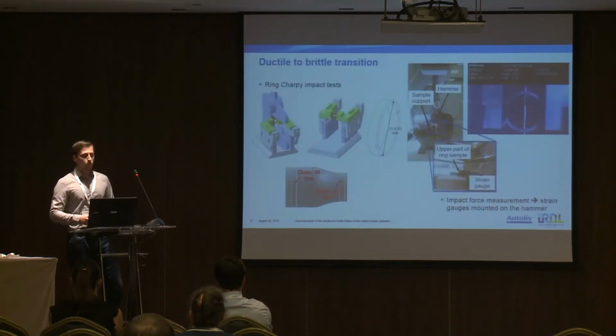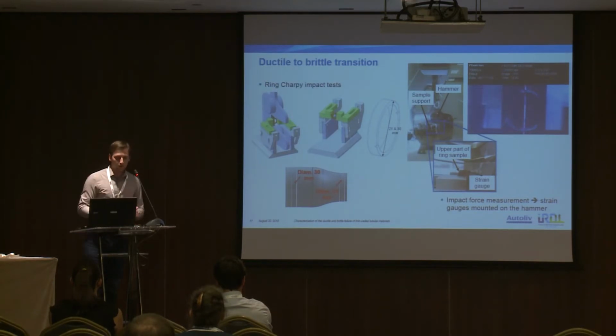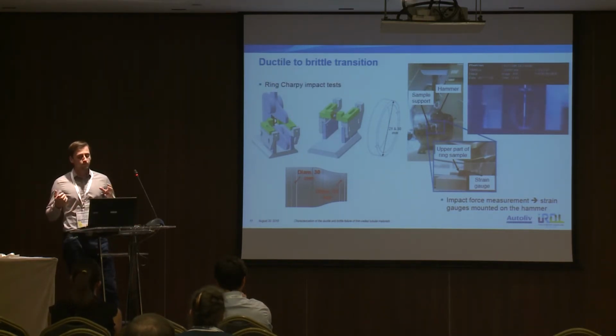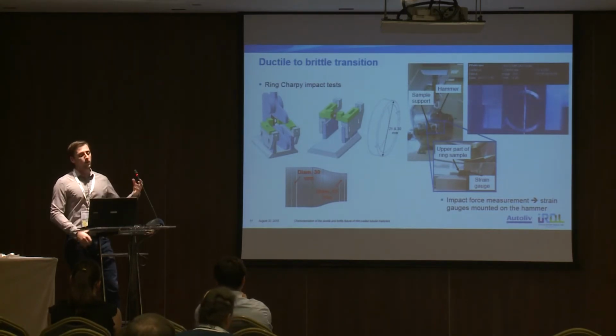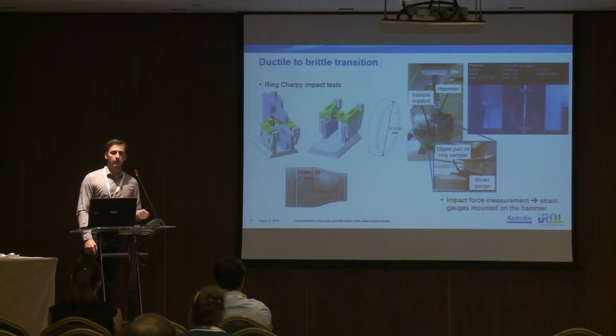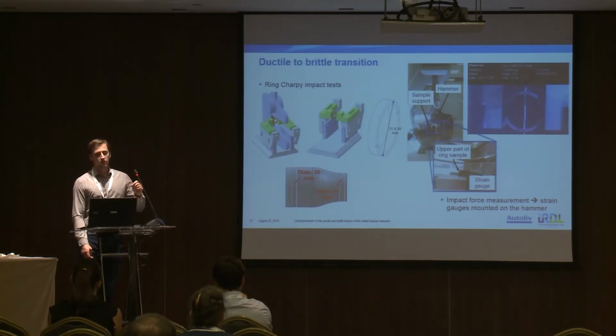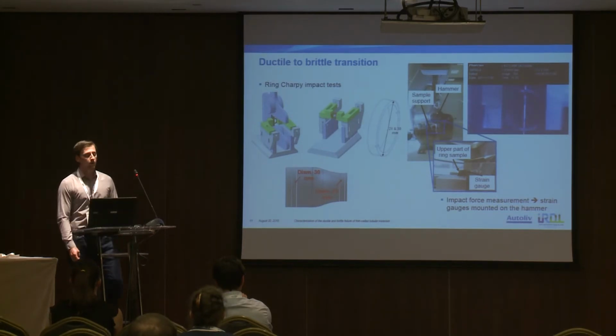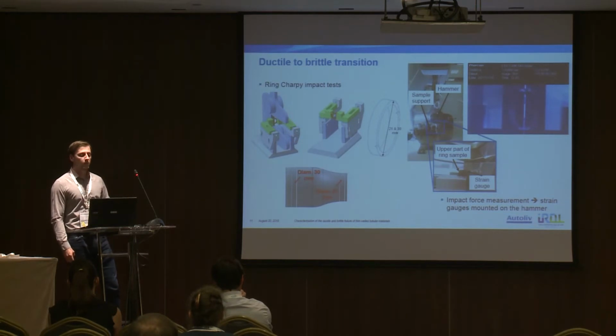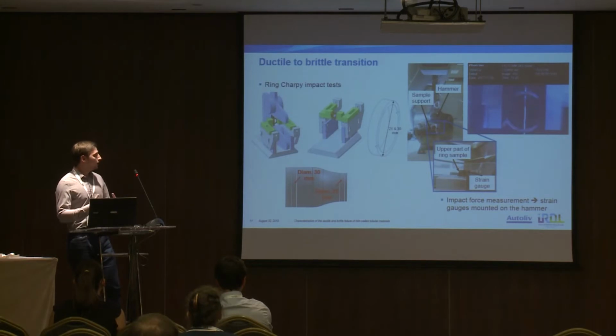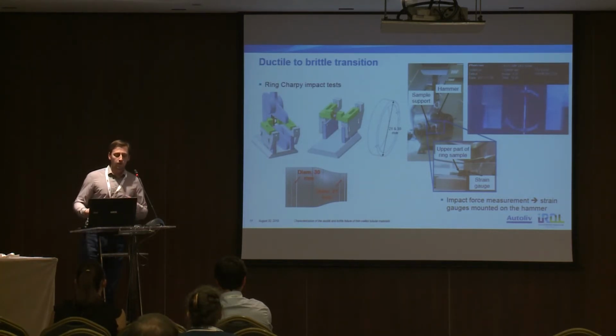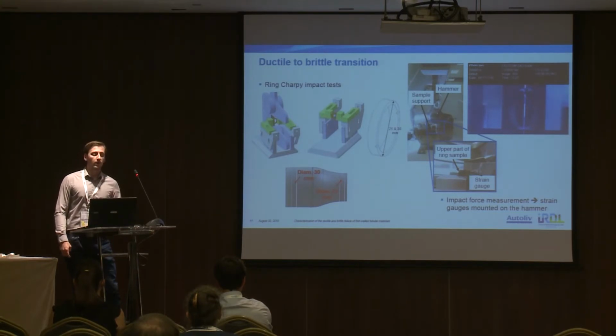Yeah, perfect. So, in order to identify the ductile to brittle transition, we have some difficulties because here we are using, of course, Charpy impact tests. But as you know, in order to have Charpy impact tests, generally we use coupons. But here we have a thin-walled tube. So we have to define a new sample geometry, and here we are using a ring Charpy impact test. Of course, specific devices in order to correctly maintain the sample were developed, and then we tried to realize some tests.